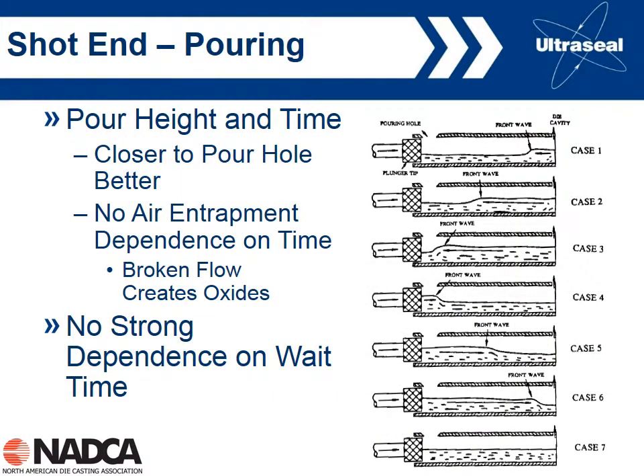So let's move on and talk a little bit about pouring into the sleeve. Certainly, when we dump liquid metal into the sleeve, it's going to move around. Is this going to affect the formation of the wave during the slow shot velocity? We'll talk about that in the next few slides. But certainly pouring closer to the pour hole is better because we're minimizing the height over which we're pouring. Pouring smoothly helps as well. We shouldn't stop and start. That can create broken flow, can create oxides, and problems with our castings.